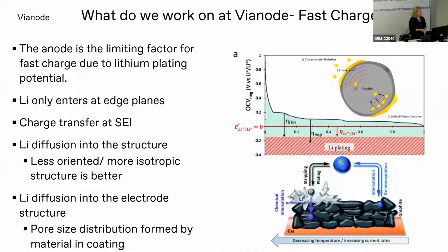And just to give you some example of what we work on at our technology center with graphite, you know, graphite is still a material that's in development. One of the most important features that we see about graphite is that the potential of graphite is actually so close to the potential of lithium metal, which you can see in the top chart. As you insert the lithium ions into the graphite, the potential can get quite low and close to the potential of the lithium metal. So if you try to push the ions too fast at the surface of the graphite, you can form metallic lithium on the surface, which is called lithium plating, and it ruins your battery.